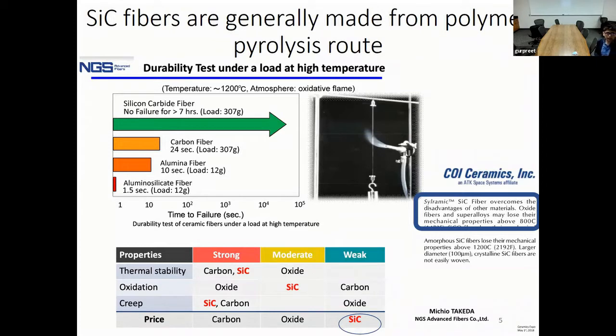However, these silicon carbide fibers, the non-oxide ceramic fibers, have one shortcoming, which is their high cost. These silicon carbide fibers are derived from polymeric precursors called carbosilane. These carbosilanes are notoriously difficult to manufacture because it's a multi-step process, and then the pre-ceramic polymer needs to have a certain molecular structure in order for it to yield phase pure silicon carbide fiber. So that increases the cost, and the market for the silicon carbide fibers is small compared to carbon fiber.